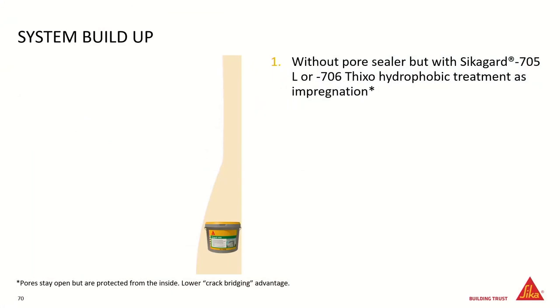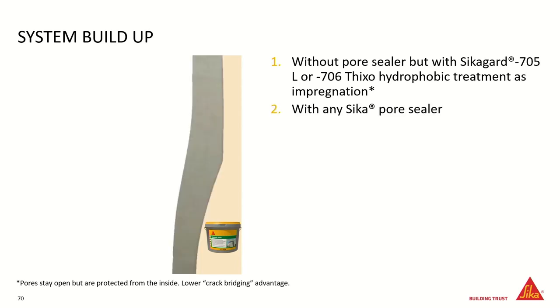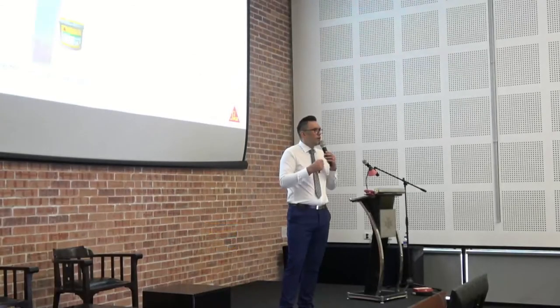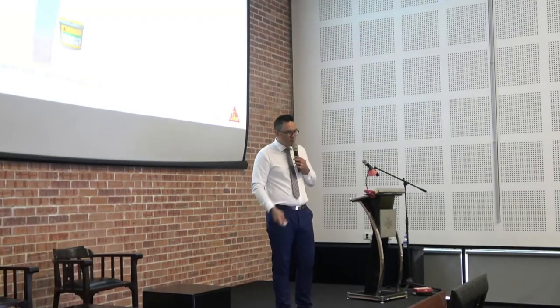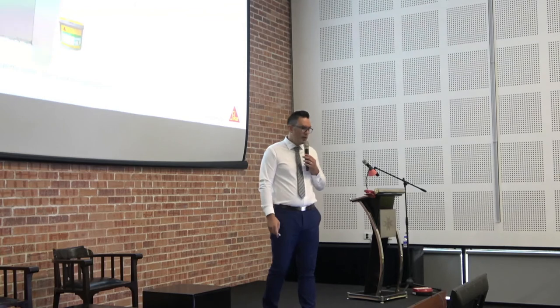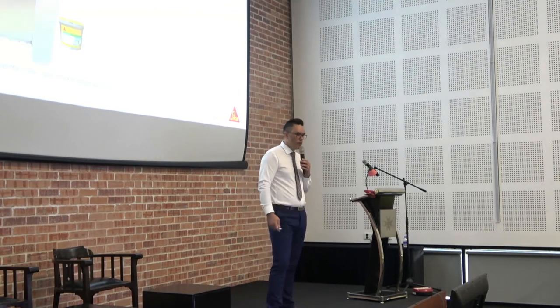The system build-up is without a pore sealer, but you can use those hydrophobic impregnations as the first primer, so that you have that double layer barrier again. You have the hydrophobic behind the coating. And then you can use any Sika pore sealer, so a cement-based leveling render to make it look nice. And there's an over-the-top of repairs.